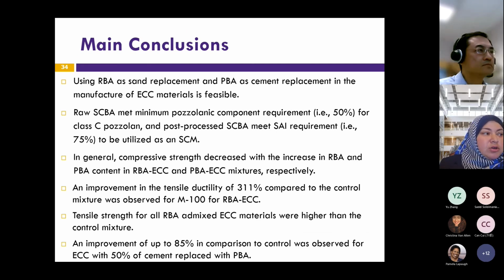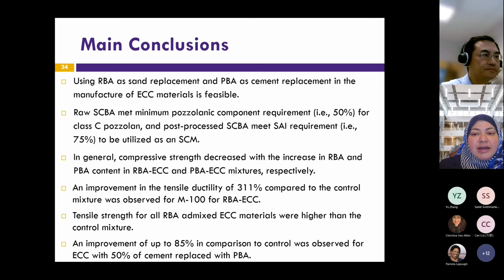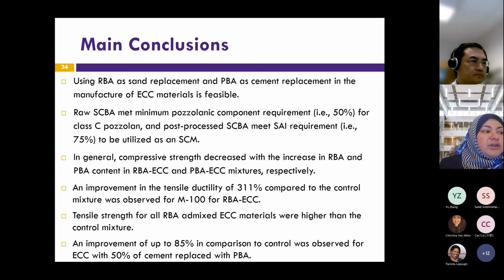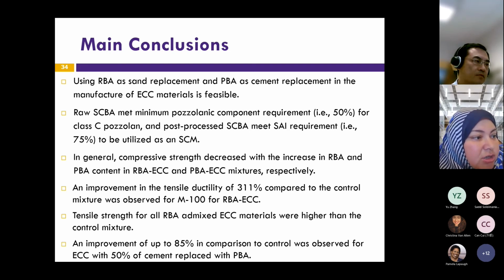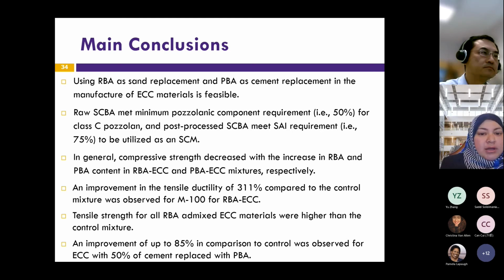So here are some main conclusions that we found. Raw bagasse ash met the minimum pozzolanic component requirements for Class C pozzolan, and post-processed ash met the SAI requirements to be utilized as an SCM, which is great. In general, the compressive strength decreased with an increase in the raw bagasse ash and the post-processed bagasse ash in the mix.